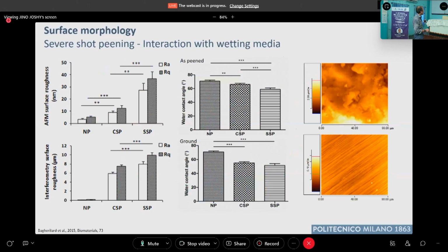In this case, there is an effect of both conventional shot peening and severe shot peening. And indeed, what is the difference between these two graphs? Here we have performed both conventional and severe shot peening, and this is after this treatment, but after a final soft grinding to have the same roughness on the different surfaces. So to make more evident the effect just of the microstructure.